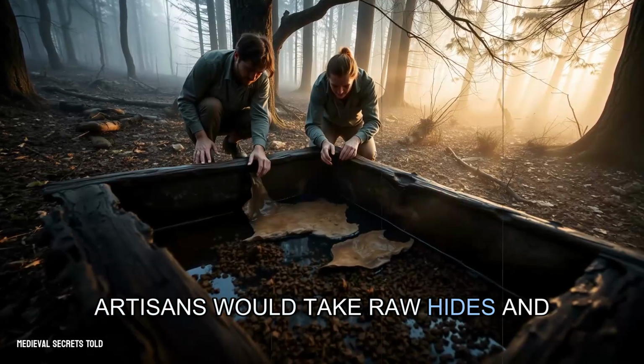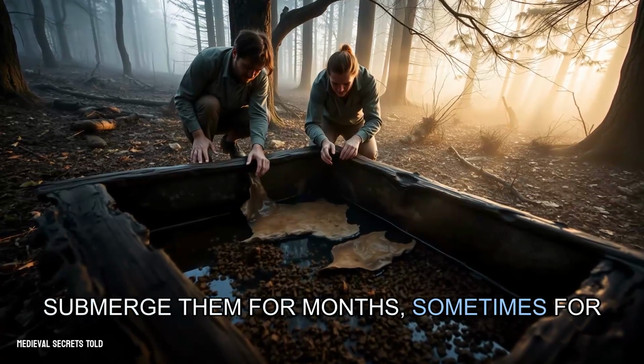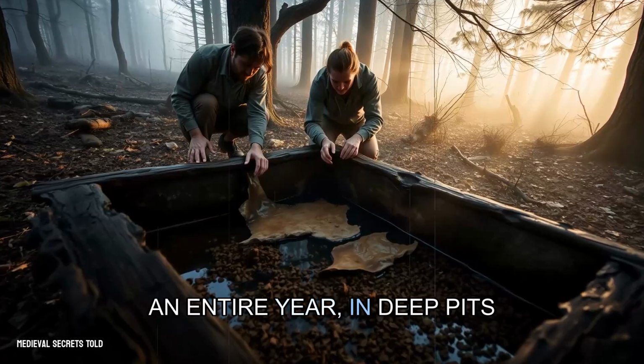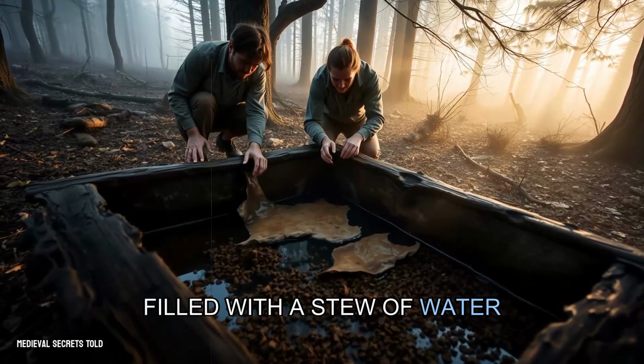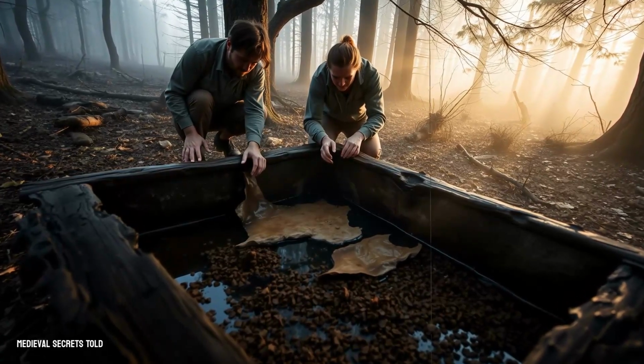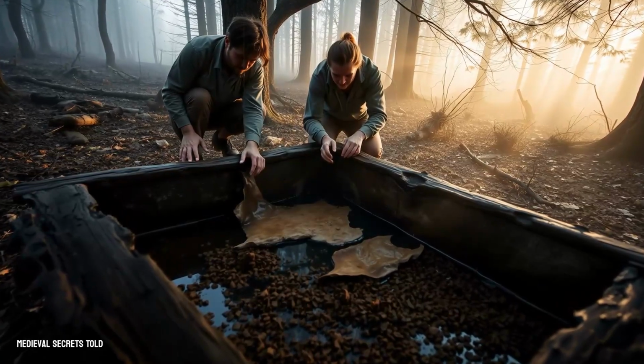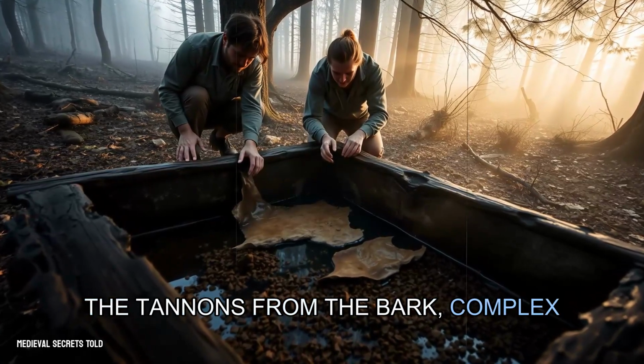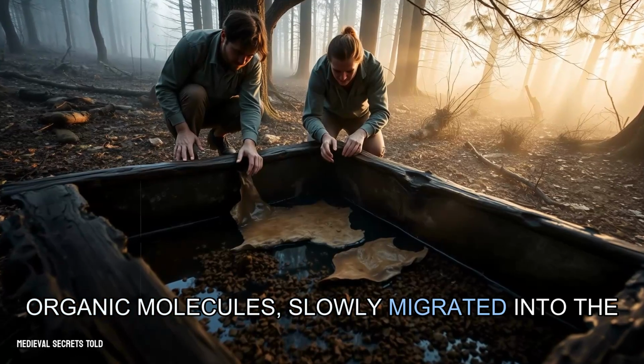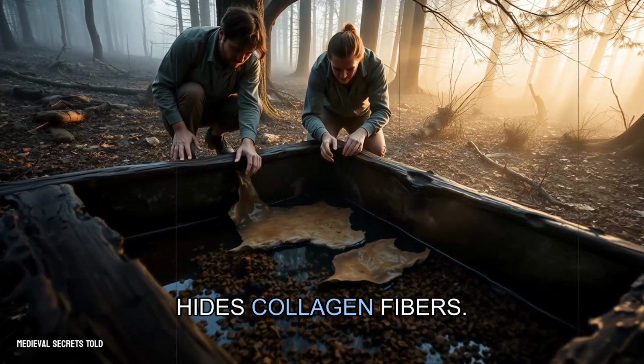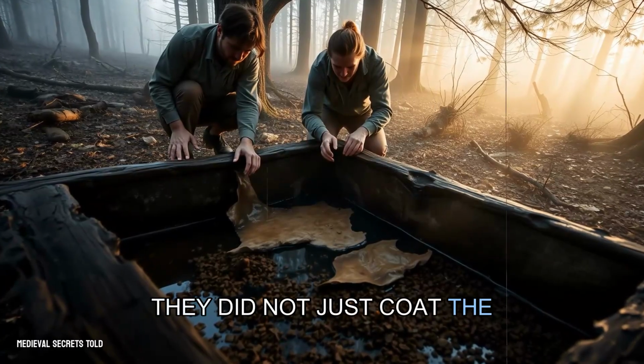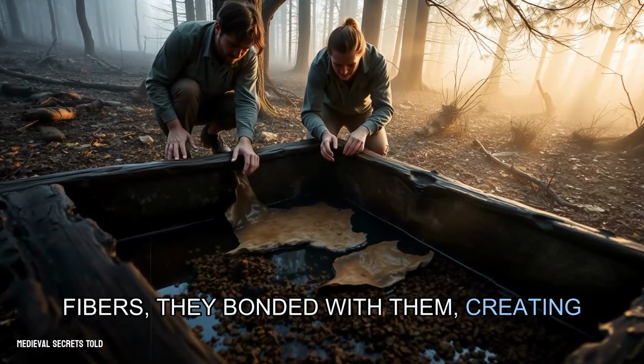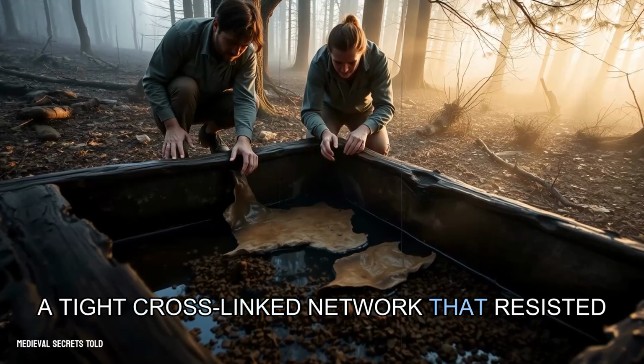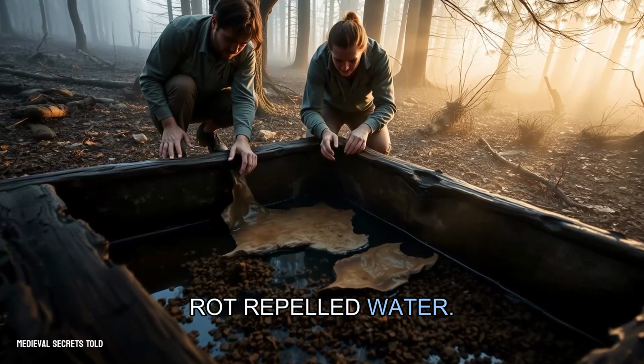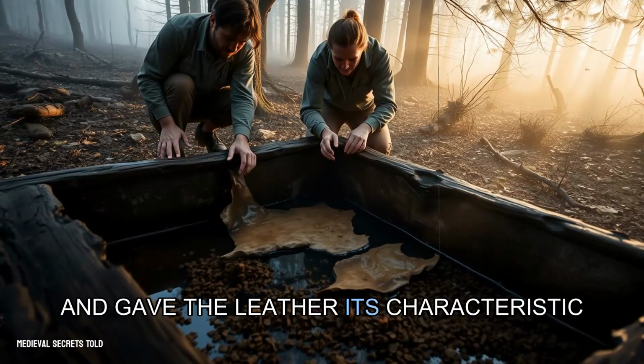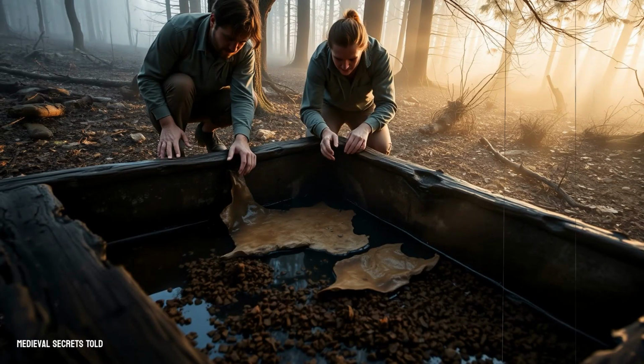Artisans would take raw hides and submerge them for months, sometimes for an entire year, in deep pits filled with a stew of water and crushed oak bark. This was not a simple bath. The tannins from the bark, complex organic molecules, slowly migrated into the hide's collagen fibers. They did not just coat the fibers, they bonded with them, creating a tight, cross-linked network that resisted rot, repelled water, and gave the leather its characteristic strength and flexibility.